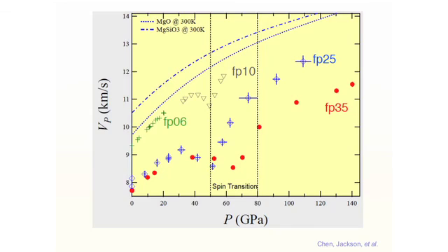And if we measure the wave velocities, we see that they are also anomalous. If we look at these lines here, that describes normal material. Velocity generally increases with increasing pressure, and this is work that postdoc Bin Chen is working on. But as soon as we add iron into the system, indicated by these numbers, or the amount of iron in the oxide, we see that it increases first and then decreases, and then increases again.